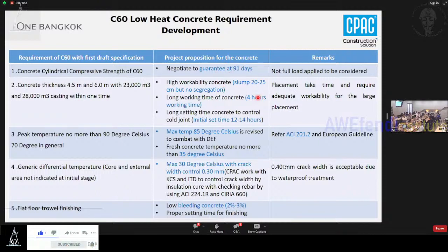So this is the number that we talked about. We would like to have high workability concrete because we cast a lot, you can imagine, 28,000 cubic meters. We need high workability concrete and long working time, around 4 hours, and the setting time we set around 12 to 14 hours. The maximum temperature, as I mentioned, is 85. The fresh concrete temperature we control around 35 degrees Celsius. The maximum temperature difference we talked about is 30 degrees Celsius in general, but in detail, we have a model from Professor Somnik and SIT to calculate the steel rebar to confirm that the crack can be controlled. The crack control for this project is around 0.4 millimeter acceptable, because after this they are going to do a waterproof treatment on the structure.